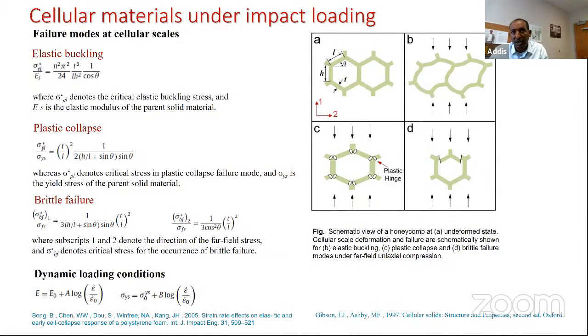Having the full field measurements allows us to understand the stress-strain response of these materials. But cellular materials are made of some parent material which has specific properties, plus geometric factors, and their failure mode depends on the geometry too. Under quasi-static loading, it is well understood that the failure modes at the cellular scale can be calculated based on the parent materials as well as some geometries. For example, you can say this is based on elastic buckling or plastic collapse or brittle failure. This is recorded in the Ashby book.